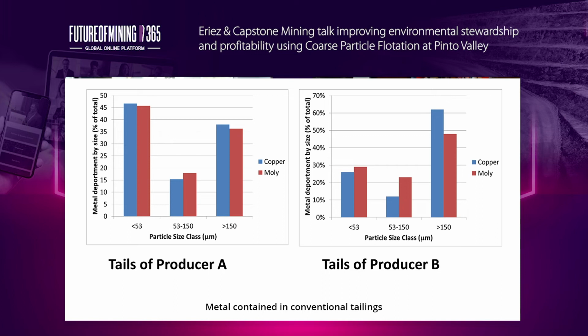This data shows metal contained in tails from two major copper porphyry producers, each greater than 100,000 ton per day operations. These histograms illustrate the serious shortcomings of conventional flotation. They're good at recovering the middling size particles, but fines and coarse are missed, and they typically account for 85% of all metal losses. Eriez flotation has the StackCell to improve the recovery of the fine fraction, which we'll talk about in another video.